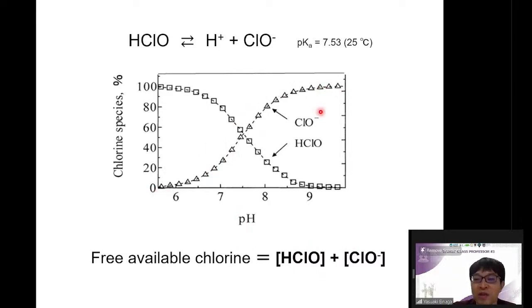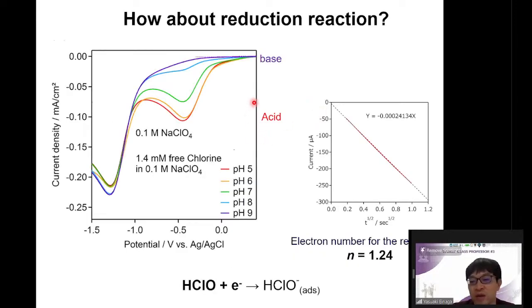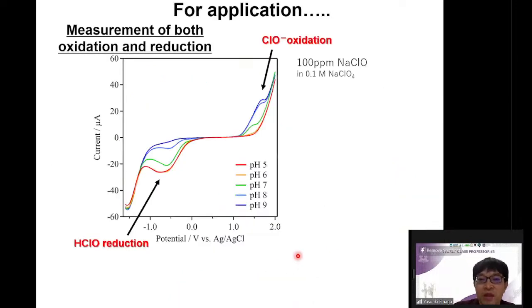So then we tried to study the reduction also. In this case, we focus on the reduction reaction also. As you can see, the reduction peak also shows a pH dependence. When the pH is low, the reduction peak appears, and when the pH is high, the reduction peak disappears. So this reaction also shows almost a 1 electron reaction. So we confirmed this reduction reaction is the HClO reduction.